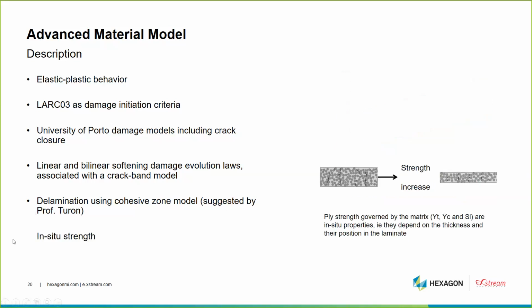The model handles also the in situ strength. So the in situ strength is a modification of the strength of the ply, so only the strength that is governed by the matrix, so the transverse tension, compression, and the in-plane shear. So it's a modification of those 3 strength values based on the localization of the ply in the laminate.